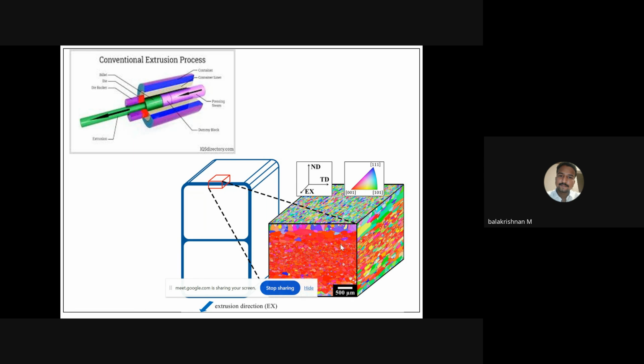But even if we go for EBSD up to 0.34 micron, it can be easily observed. This kind of change will not support enhancing the strength of the material, but we can get grain refinement on the surface area.